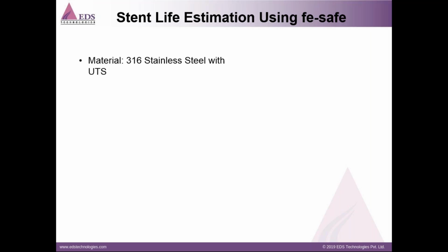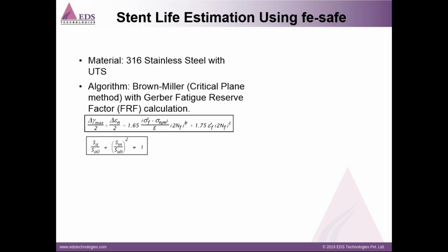The fatigue life estimation using the fe-safe tool is discussed in this slide. The material used is 316 stainless steel with its ultimate tensile strength. The algorithm used for estimating the fatigue life was Brown-Miller with the critical plane method, for which the Gerber fatigue reserve factor was computed using these equations shown on screen. Infinite life was also studied for 2e9 half life cycles, which is approximately 20 years equivalent.